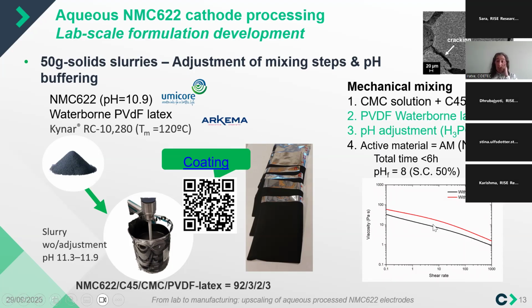There is no gelation with the addition of PVDF and the phosphoric acid, which in some NMC systems can be an issue. So in the rheology, it's always important to check the rheological properties, and not only the pH, to be able to say that these waterborne slurries can be upscaled and processed. So this is the kind of rheological behavior that we would want.